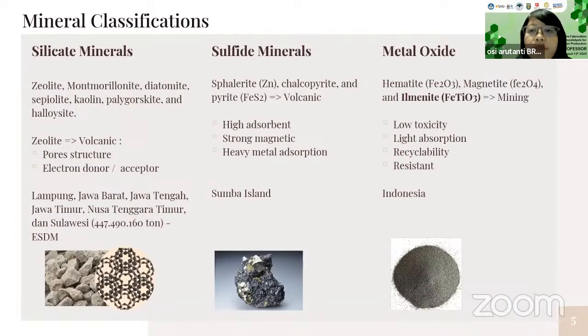And then the last one is metal oxide. For example, hematite, magnetite, and ilmenite. Here, I will focus on ilmenite. Ilmenite is one of the side products from the tin mining industry, and the composition of TiO2 in ilmenite is usually around 60 to 80%, depending on the type of ilmenite. We can use metal oxide as photocatalyst material due to the characteristics such as low toxicity, light absorption, recyclability, and also resistance. And yeah, ilmenite in Indonesia is abundant.